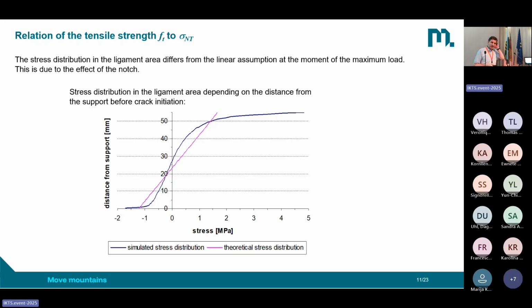So what is the reason? The reason is simply that we have a starter notch, and around the notch we have a stress concentration. That's why we have this increase here. And at the bottom, the sample is resting on a support. That's why we have higher compressive stress here.